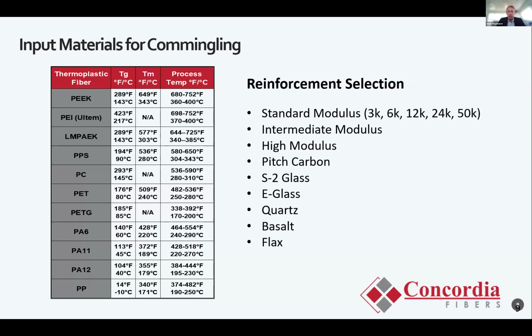And then on the right, we have a whole selection of reinforcing fibers, and it's pretty much the same reinforcing fibers that are used in thermoset composites, from various size standard modulus carbons from 3K to 50K to intermediate modulus, high modulus pitch carbon of various stiffnesses, e-glass, quartz, basalt, flax, hemp, aramid, metal fibers are all things we've included. Some things that are interesting on this list here, combining PA11 and flax or hemp yields more of a bio-based, easier recyclable or end-of-life type material combination.